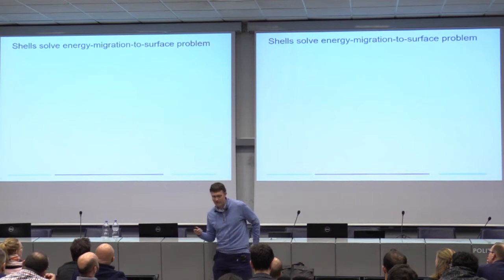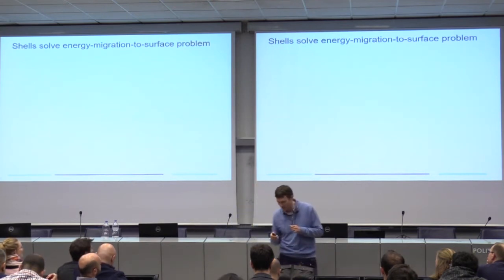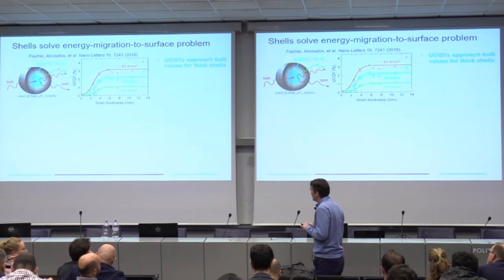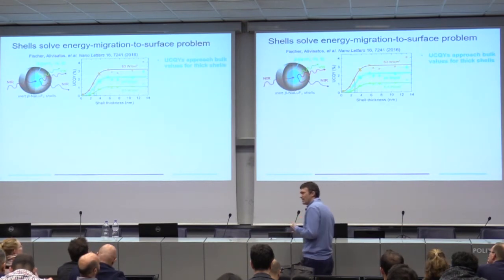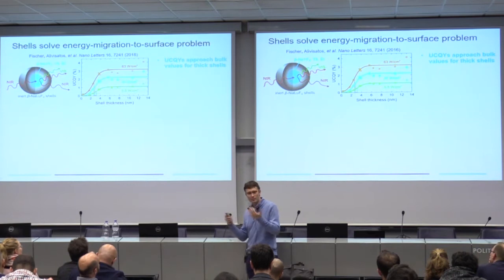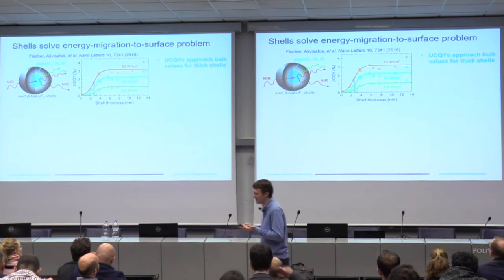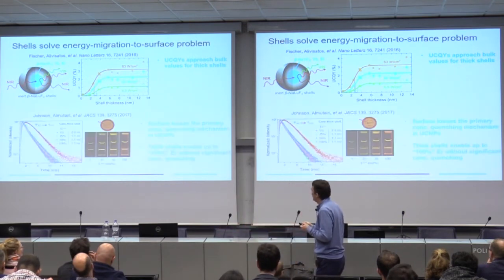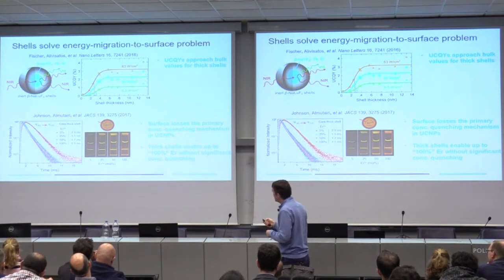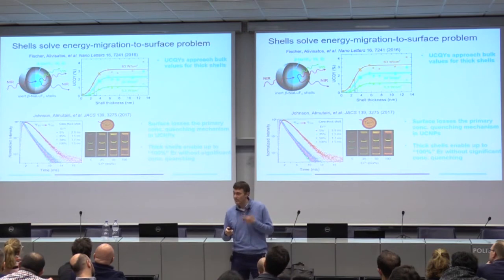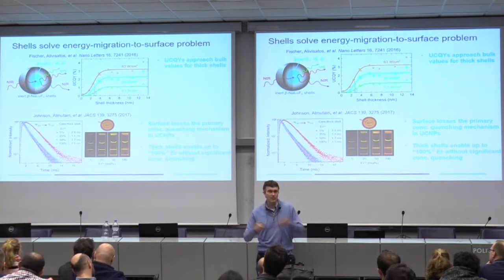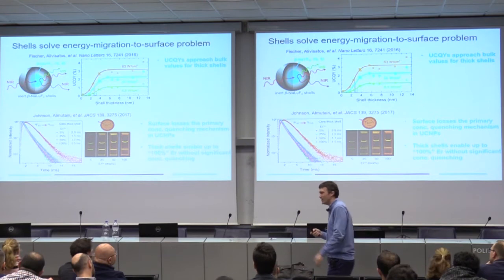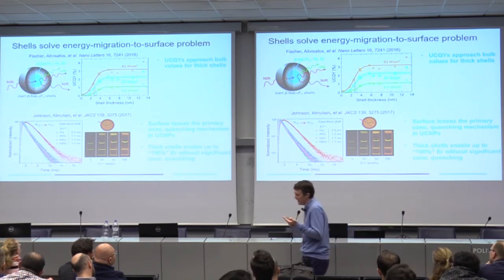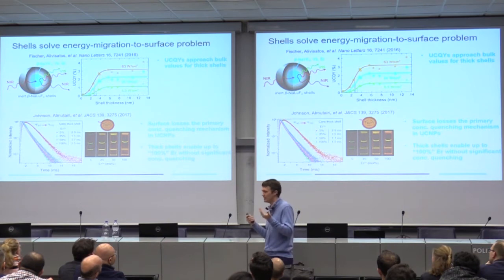The next step to making them brighter is actually something that makes a lot of sense. It's something that really is almost trivial, which is you can put passivating shells on the outsides of your materials, and this helps with this sort of energy migration to the surface. This basically alleviates all of your surface losses. And so what people showed after our paper was that, yes, you can put these inert shells on your material, and once you do that, you can now increase the emitter concentration basically up to the maximum, up to 100% of emitter, or 100% lanthanide, usually maybe 20% of ytterbium and 80% erbium, for example.